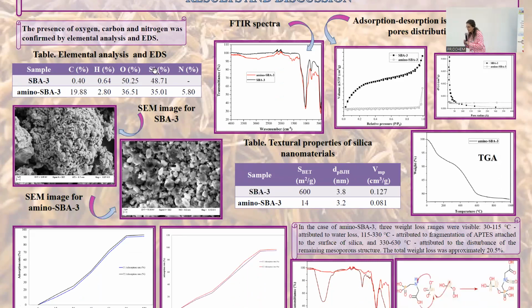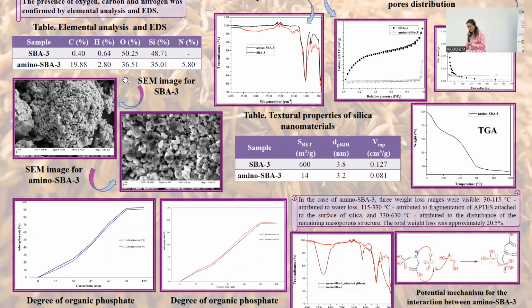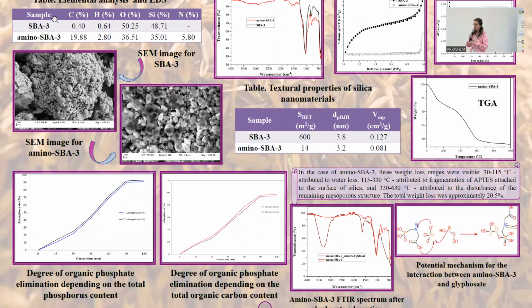Sorry again for my voice. The glyphosate adsorption was monitored photometrically by determining total carbon and total phosphorus content in two solutions that we prepared according to the solutions that every agriculturist used, and also for the concentration that was found in wastewaters. As you can see, after 90 minutes, an equilibrium of adsorption was achieved, and this was the time that we took into consideration for our Langmuir and Henry models.